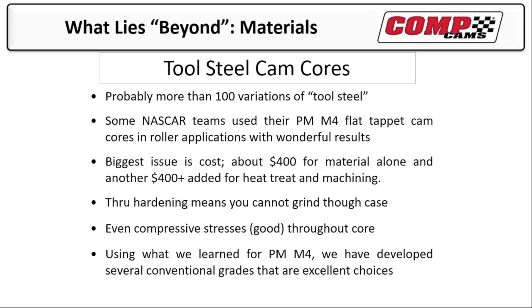The problem you might have in 8620 or 5160: if you grind 50 thousandths off one side and 10 thousandths off the other, somewhere you're transitioning between a deep case and a thin case. Where it's deep, it has more compressive stress, and where it's shallow, it has less compressive stress. So you get more deflection. That uneven loading can cause spalling from the bottom. And that's why we really want to make sure that when we're taking a core, that we grind it properly.